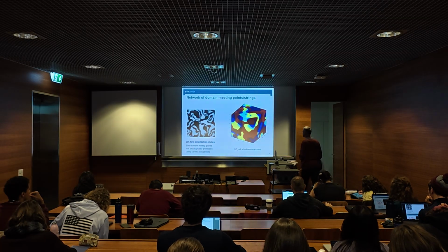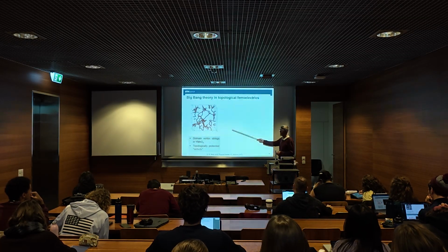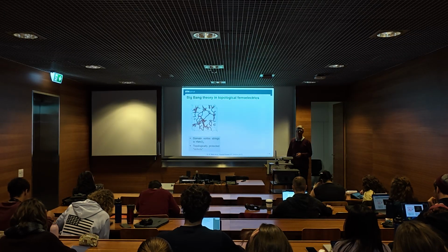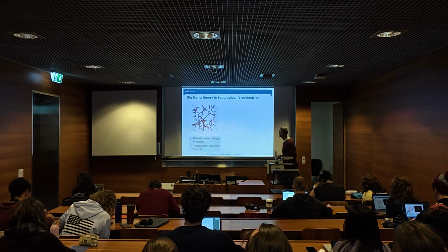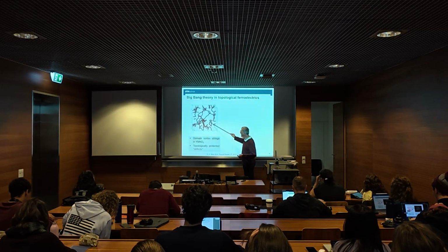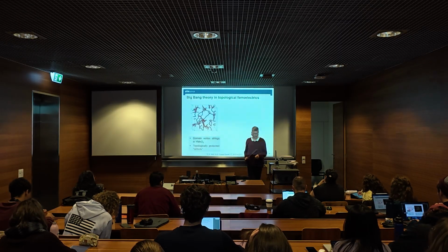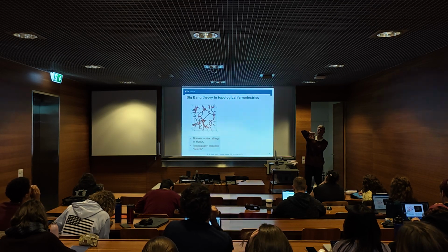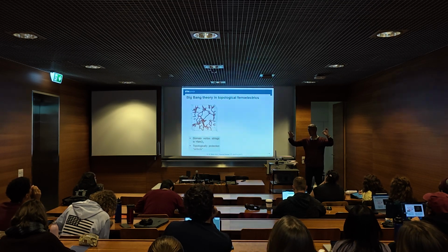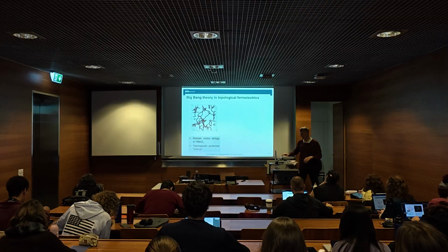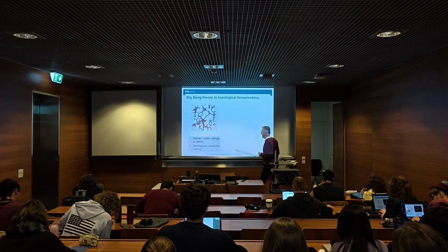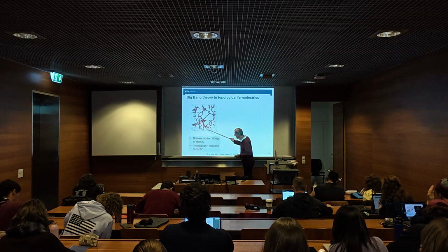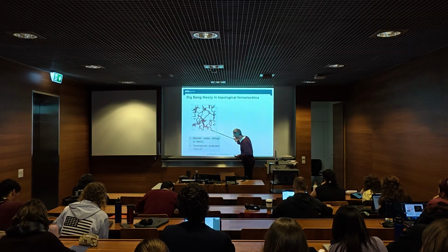Yeah. So if you plot these lines, then this looks like that. This is one of the frames that I just showed. And then you would say, okay, fine, it's a box full of noodles. Now, not exactly, because noodles don't form loops. These need to form loops, and also if you think about the domain configuration, what is not possible is this kind of loop. That's not possible. So they are all separate loops that meander through your material. The only point where they are not loops is when they are cut by the surface. Then if the crystal continued, it would be a loop.